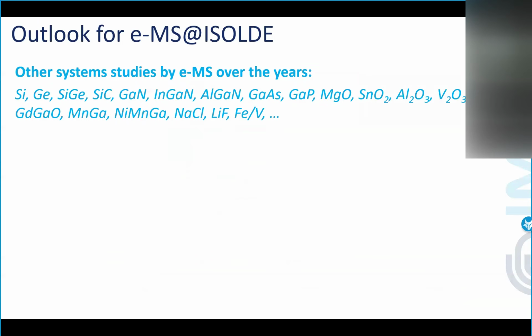Now, I don't have a conclusion slide because I hope I gave some separate conclusions step by step in this example, but just conclude with this one. As Davide said, the particular feature of this method is that you can perform this spectroscopy ideally on all the materials, regardless of whether they have iron or not. And this is a list that I took from papers that we published in these years, probing hyperfine interactions upon implantation. In some of them, there is manganese, and this is nice because you expect that your manganese goes there. So you expect it's substitutional and you look at what happens around.